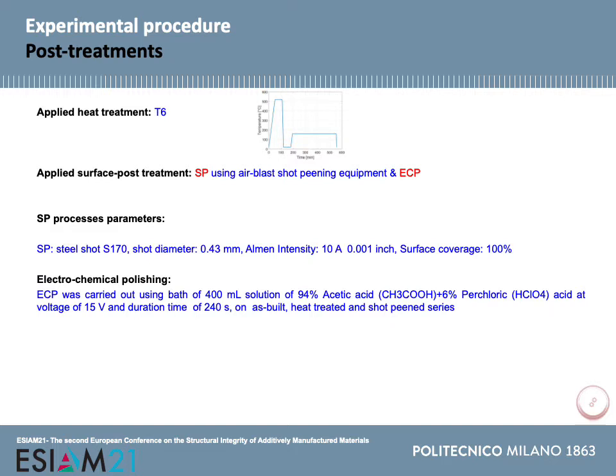In the shot peening treatment, steel shots with diameter of 0.43 millimeter with Almen intensity of 10A and surface coverage 100 were used. Also, in electrochemical polishing, 400 milliliter solution of 94% acetic acid with 6% perchloric acid at voltage of 15 volts and duration time of 240 seconds were carried out.